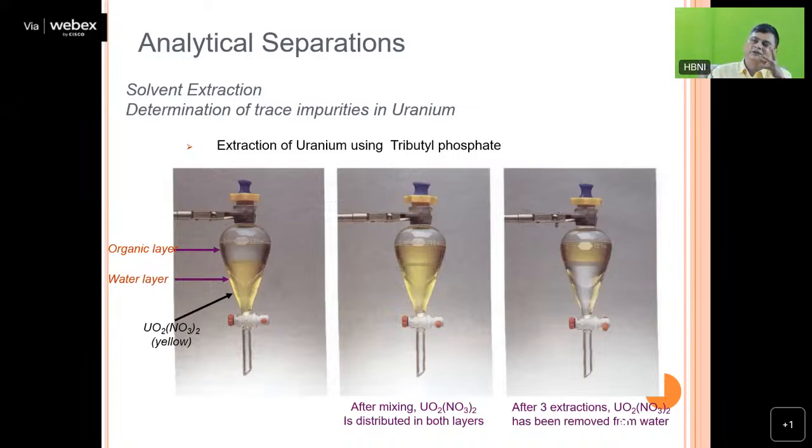I can dissolve the uranium sample in HNO3, but I will not get any result because of spectral interference, unless I remove the bulk of the matrix, which in this case is uranium. So to perform this analysis, I use the method of solvent extraction. By using solvent extraction, I remove the total uranium from that bulk material, and then do the analysis.